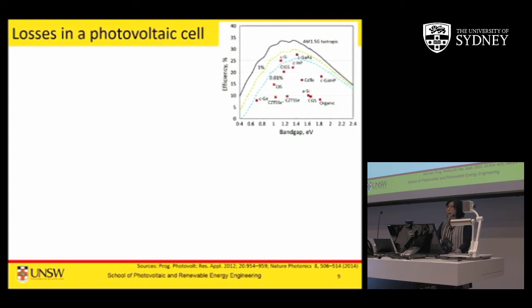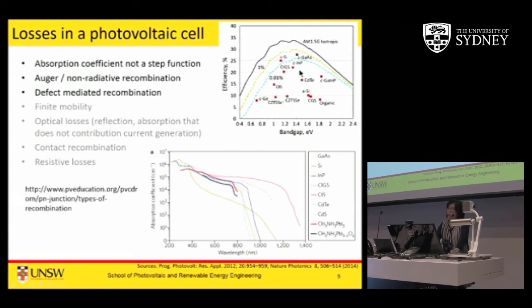I'm explaining the maths and physics behind how you derive a solar cell diode curve. Everybody who lives and breathes solar cells knows what the IV curve is about - the job is to report the best IV curve they can make. We calculated the efficiency limits for a single band gap or single junction solar cell, but in reality the best cells made in the world are all below the theoretical curve. Why? Because materials are not perfect absorbers. If a material has a band gap of 1.1 eV, we assume it absorbs everything above 1.1 eV, but in reality that may not be the case.